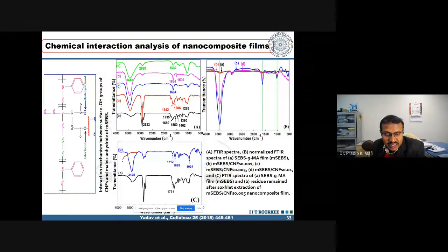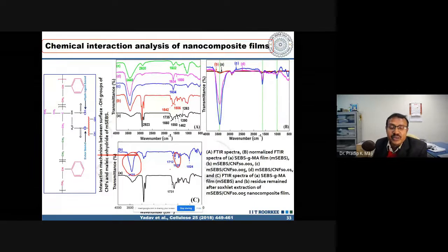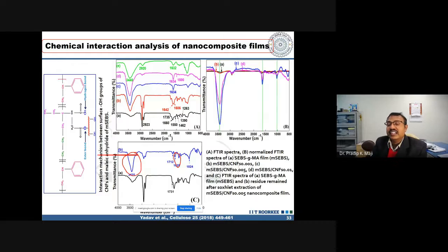And yes, you see this is the cellulose peak, the OH peak. There is a cellulose peak at basically 1628, and that's why we can conclude there is an interaction between the cellulose and the maleic anhydride. That's why it has given the mechanical reinforcement.